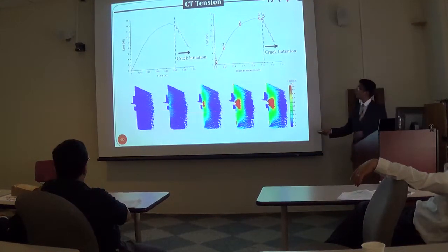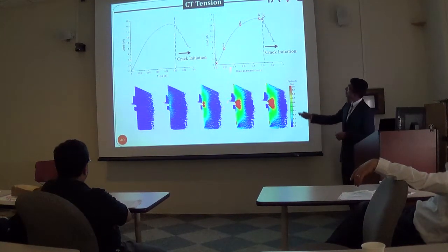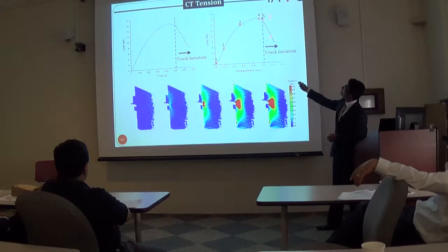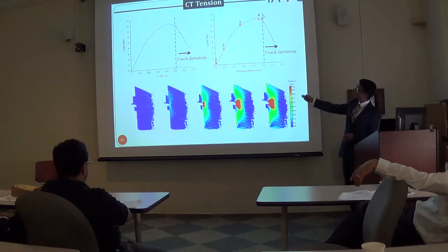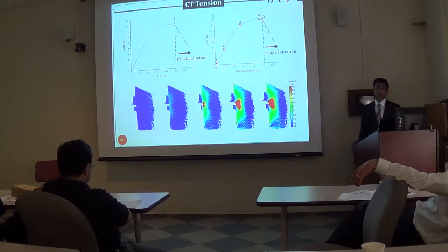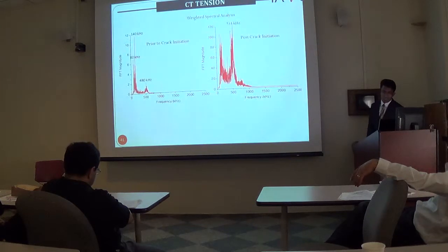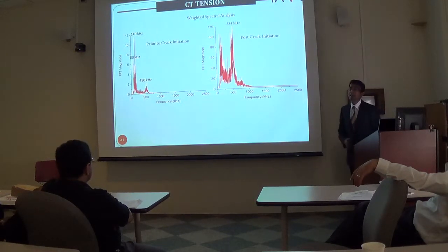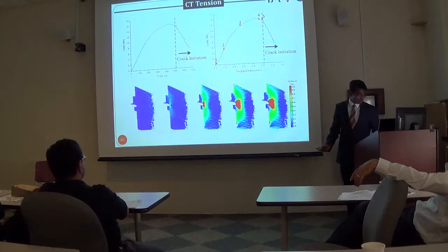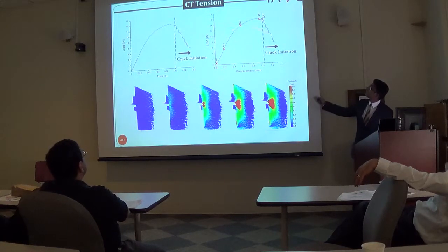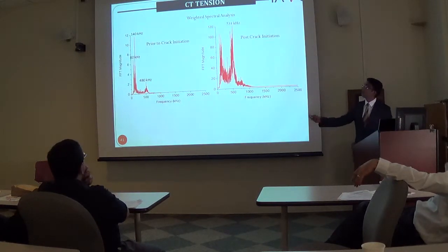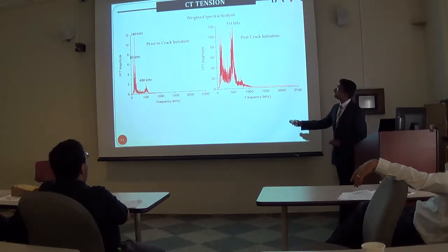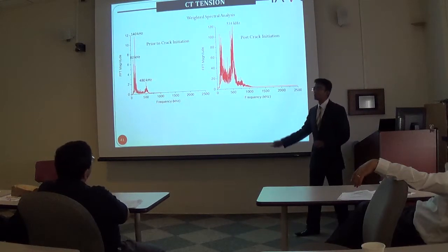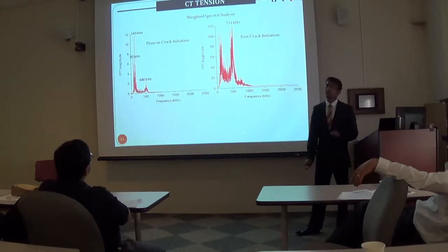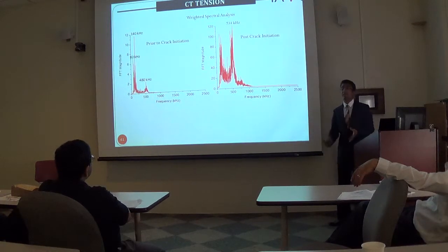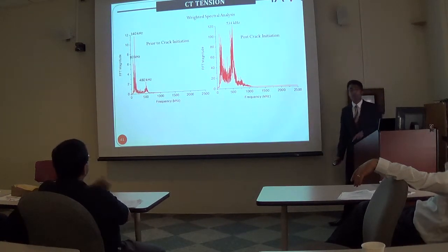So the full field strain maps show how the plasticity grows at various points in the load. And exactly at point 5, which is just after the initial load drop, you can see the onset of crack initiation. Now this was then utilized to interpret and analyze the AE signals. So the signals that were picked up before the crack initiation and after the crack initiation were then analyzed. What I need to bring attention to here is that this is not an FFT analysis of a single waveform, but a weighted analysis of several AE signals that were picked up before and after crack initiation.